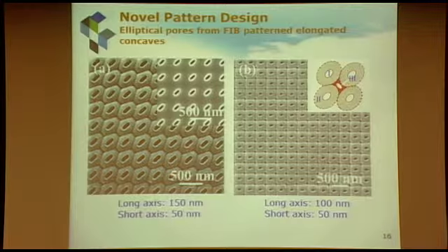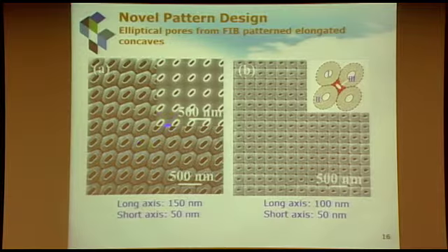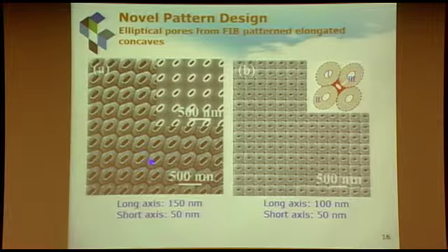Another interesting thing actually we realized we are not confined to spherical pores either. So these initially we pattern pores like this. This is kind of like unintentional discovery because the beam was not focused well. You see this elongated shape. And then when we actually anodize this, we got this elongated pore. You see the oxide layer in this picture is very, very clear. So this is interesting. We can move away. These are also not hexagonal. They are square arrangement. So this become quite interesting.